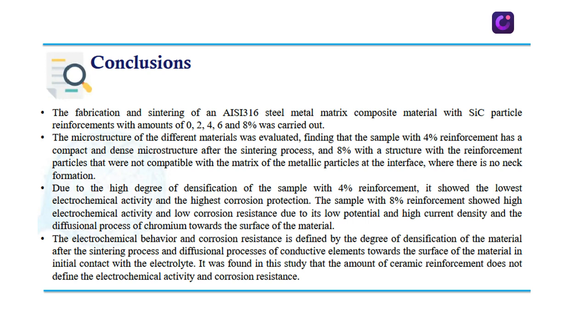In the end, the electrochemical behavior and corrosion resistance is defined by the degree of densification of the material after the sintering process and the diffusional process of conductive alloying elements toward the surface of the materials in initial contact with the electrolyte, indicating that the amount of ceramic reinforcement does not define the electrochemical activity and corrosion resistance.